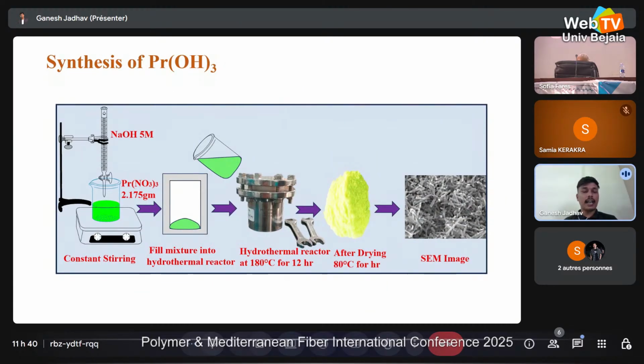This is a typical method that I have used for synthesis, in which I took PR nitrate as a precursor and drop wise addition of NaOH. Then we got precipitate, and that precipitate was transferred into a hydrothermal reactor, and that autoclave is tightly closed, and then that hydrothermal reactor is put into an oven at 180 degrees Celsius for 12 hours. After that reaction happens, we get this greenish yellow color powder, and that powder we dried at 80 degrees Celsius for 8 hours, and this is the morphology of my catalyst. We can clearly see that there are rod-like structures.